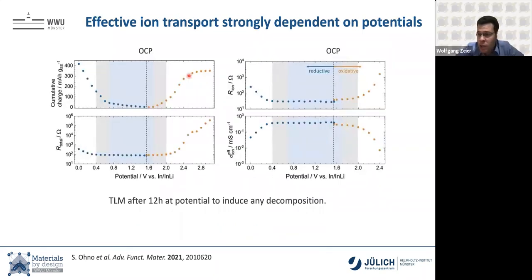So what we did is we kept using this approach of the transmission line modeling for the impedance data of these full cells. And instead of actually running these batteries, we just kept them at specific potentials for 12 hours, went back to open circuit voltage, and then measured the impedance, just to look at how the resistance in these cells changes. The first thing that we can see is here in blue is the potential range that we see based on the CVs where it should be stable. Up here is the cumulative charge. So as soon as the charge goes up, it means there's something flowing, which means we're decomposing our electrolytes. And here is the total resistance of the cell, and here's the ionic resistance of the cell.